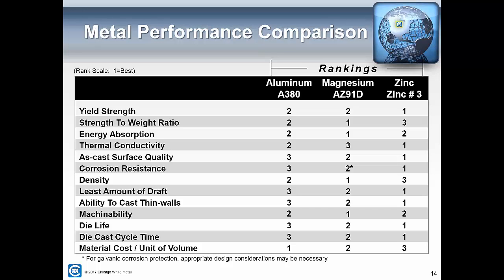So zinc from a yield strength is very effective, but obviously it's higher weight. A strength to weight ratio is the least effective, whereas magnesium claims the number 1 position in that category. Magnesium also has very good energy absorption. Thermal conductivity, zinc, though aluminum, magnesium also do a very good job of that. Surface quality, there certainly is a lot of applications where zinc is chrome plated and so on. It has excellent surface quality. Corrosion resistance also is good for zinc, not as good for aluminum.